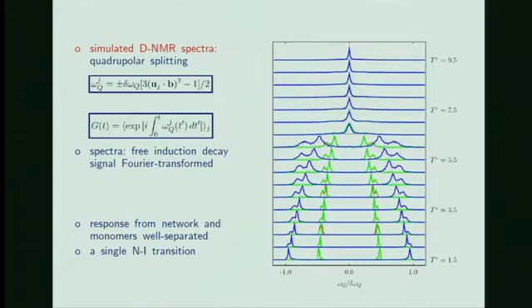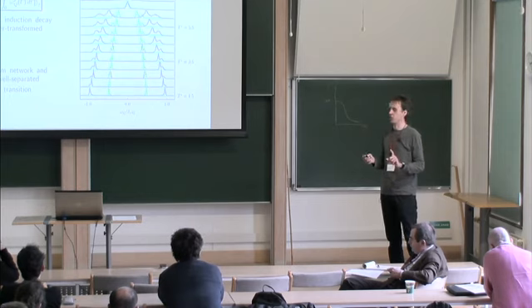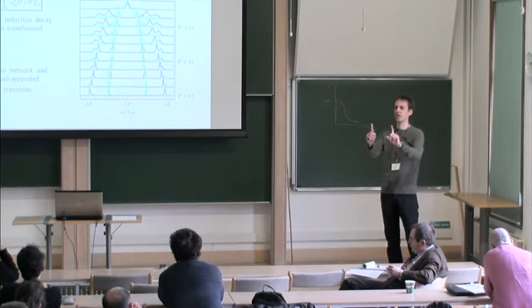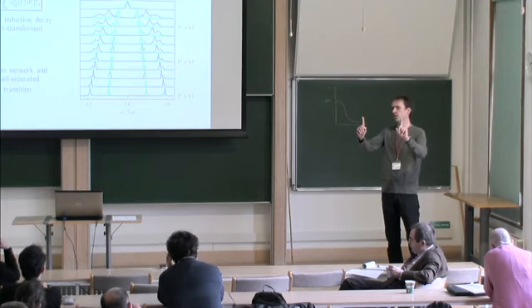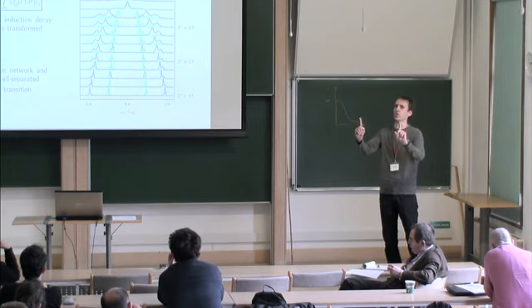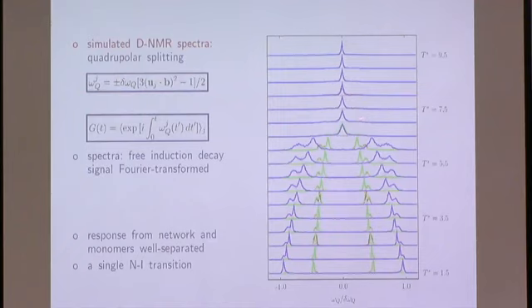For example, if you apply our NMR field along the z-axis, since the system is homogeneous, if the system was perfectly homogeneous, you will end up just with a doublet of 2 lines, and the splitting turns out to be proportional to the degree of ordering in your system. So we can see that at a high, or let's say isotropic, temperature, where we expect the order parameter to be equal to 0, the quadrupolar interactions are averaged out, and we end up with a peak at 0 splitting. Now just concentrate on the blue set of lines. For example, at the lowest temperature, we can see a nicely resolved doublet, and the system is almost perfectly ordered. So this corresponds to a very high P2, almost close to 1.